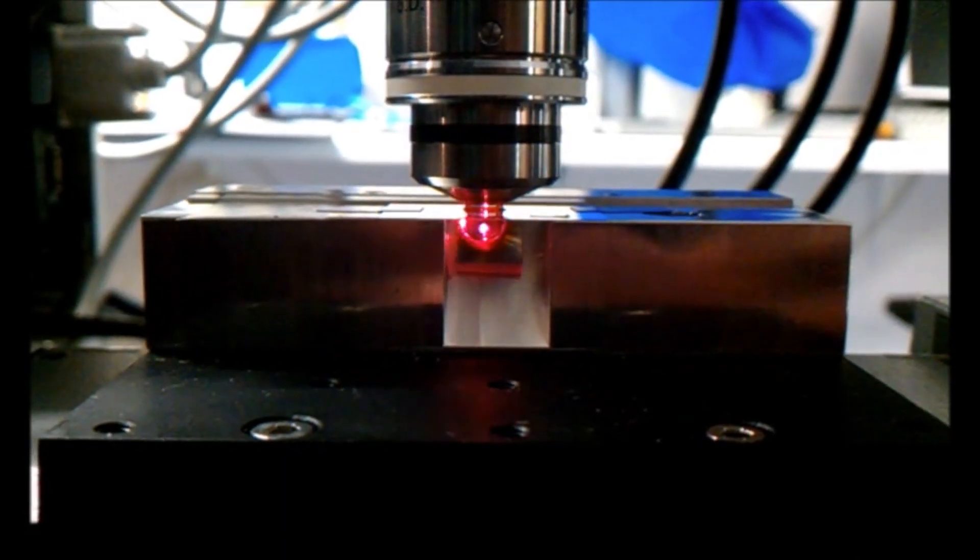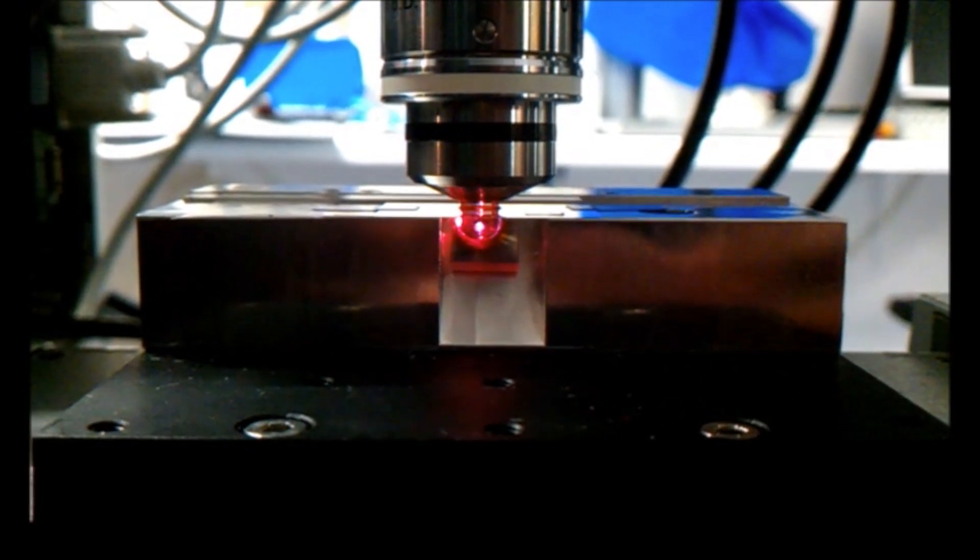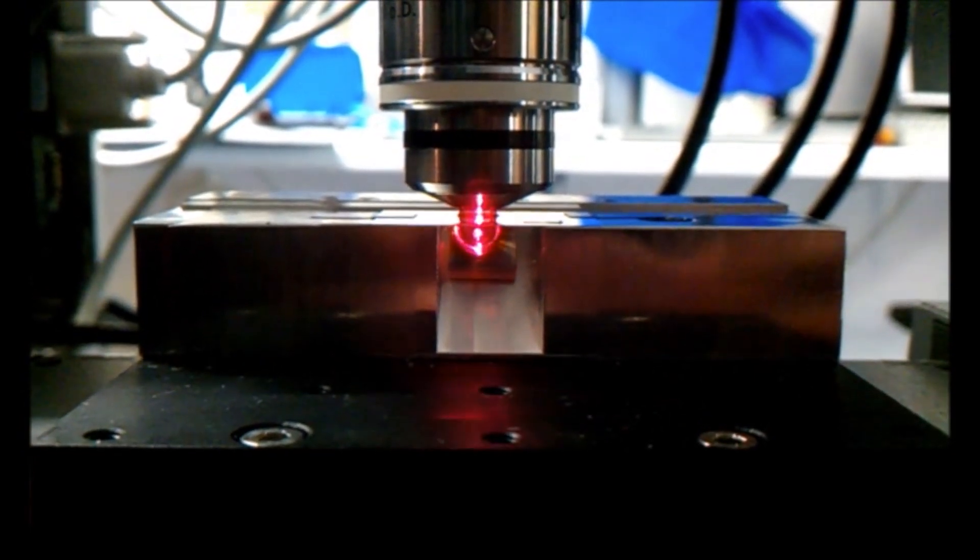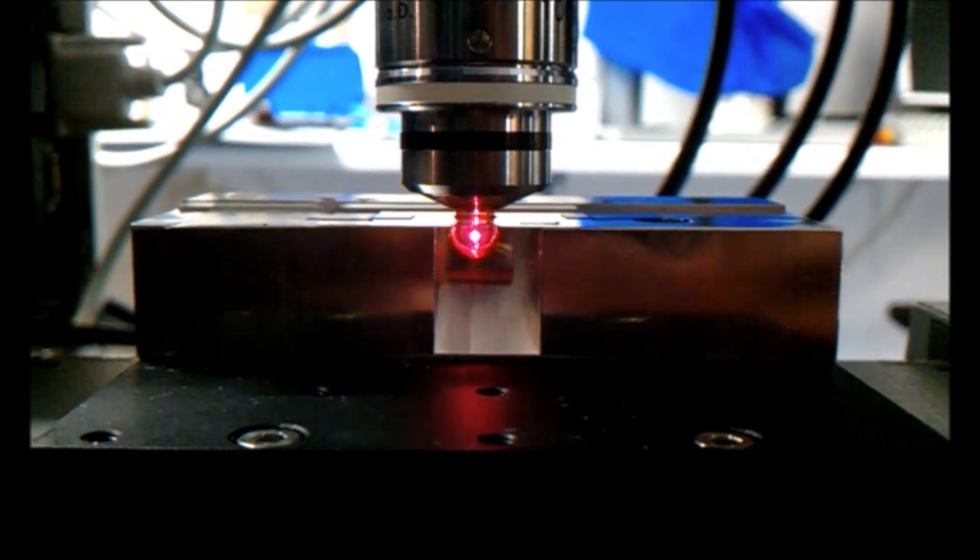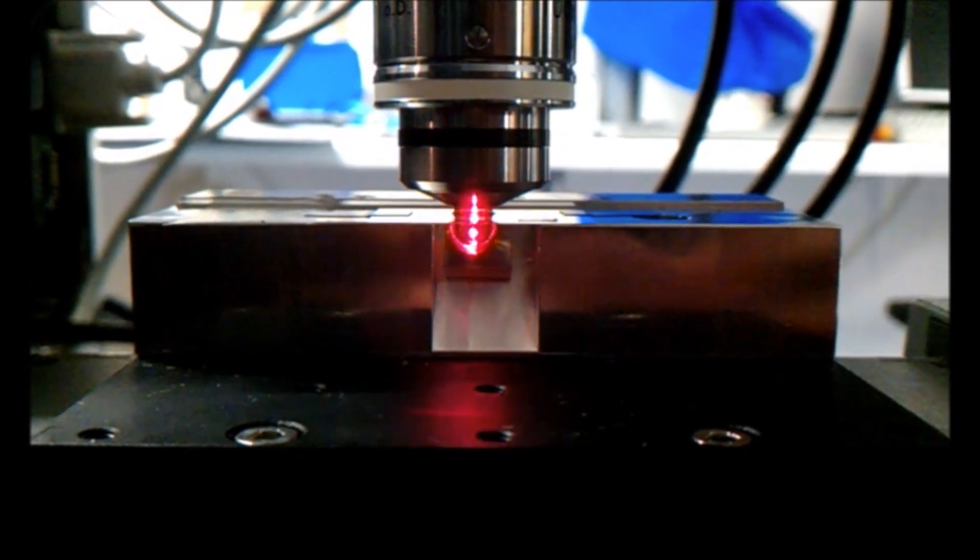This is the actual writing process of nanostructures. In doing so, the laser beam is focused 10 micrometers inside the material and a sample is moved under the objective lens with translation in x, y, and z direction.